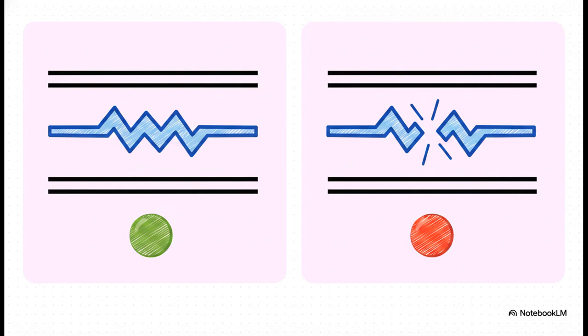When you pass a specific electric field through the memory layer, oxygen ions are literally pushed out of their normal spots in the material's structural lattice. Think of cars backing out of a crowded parking lot and driving away. They leave behind empty spaces, which we call oxygen vacancies. Because of the physics at play here, these empty vacancies actually link up, forming a microscopic physical wire, a conductive filament, that bridges the gap between the electrodes.